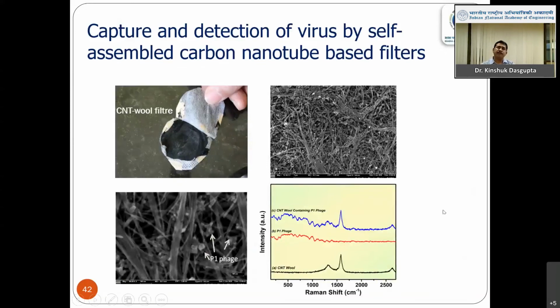And recently, we have used the carbon nanotube for the capture of, say, virus. As I have shown in the first slide, there is a methodology called carbon nanotube aerogel, which is a 3D structure. From there, you can make some kind of filter where the carbon nanotubes are randomly oriented, but the pore sizes are such that you can trap the virus. Here we have taken P1 phage, which is a virus to the bacteria, but having a dimension which is similar to that of the COVID. So we could show almost 98% of this phage material could be trapped by using a single layer of carbon nanotube filter, and